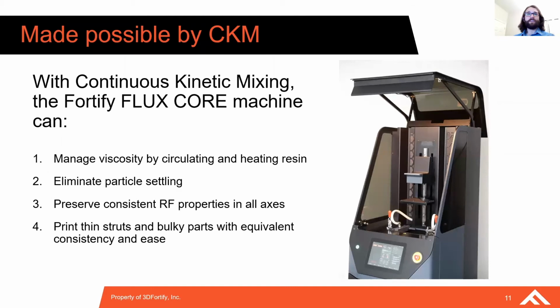And all of this is made possible thanks to a technology at Fortify we call CKM, or continuous kinetic mixing. CKM is a fluid pumping and heating system which manages viscosity by circulating and heating the resin, which helps to eliminate particle settling by keeping all those particles suspended due to fluid flow and other mixing elements. This technology helps to preserve the consistent RF properties in all axes due to the homogeneity of the material. And it also helps us to print thin struts and bulky parts with equivalent consistency and ease without a reduction in any performance along any feature.